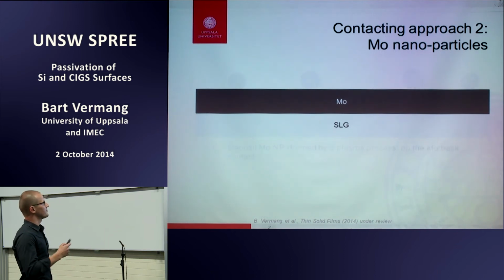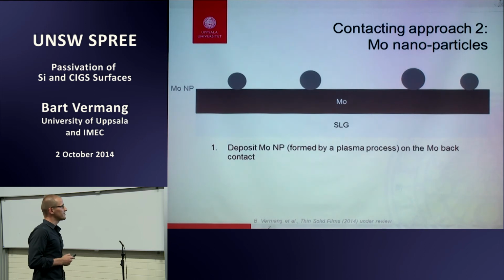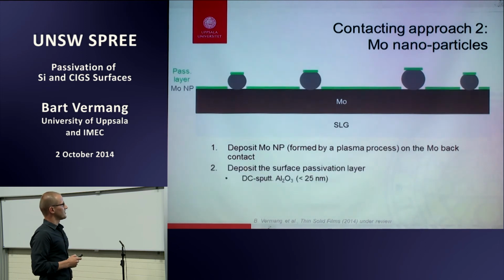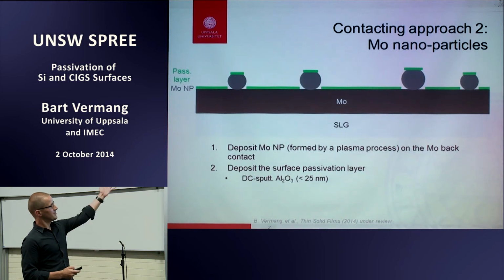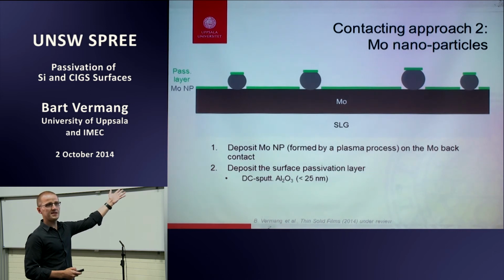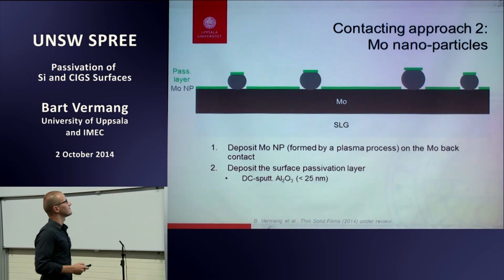So what do we do here? We deposit molybdenum nanoparticles, sputter again an aluminum oxide layer, and you have some shadowing effect, of course, by the nanoparticles, which means on top of this we can start to grow the CIGS layer and start to make cells.